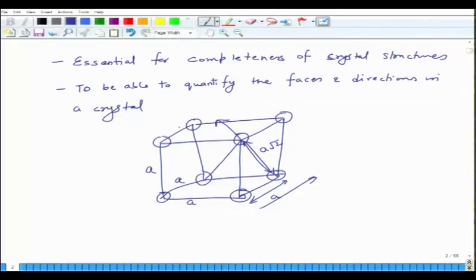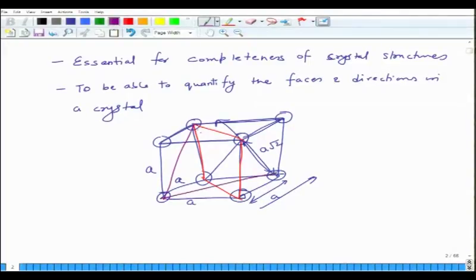Similarly, you can see that different faces of a crystal have different atomic density. For example, this face has four atoms located at certain distances. If I take this face, it has a different density — the same number of atoms but different density. This will change when you go to FCC and BCC structures. Different faces have different density and as a result they will have different responses, because atoms are packed differently in these directions. That is why it is necessary to evolve a system to quantify these things.